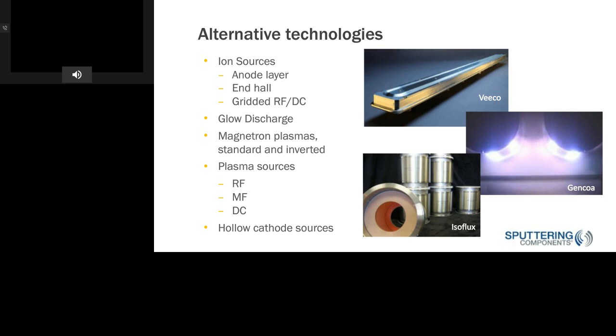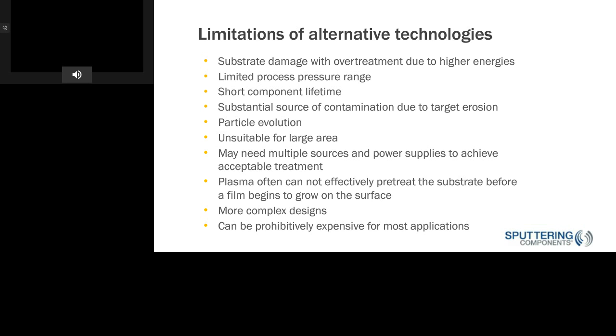slide. The main limitation really is substrate damage with overtreatment due to higher energies, and I'll show you a slide soon for the ion energies of this source versus competing technologies. The ion energies are typically much higher, and you can get substrate damage. There's also a limited process pressure range, especially with microwave plasmas. The pressure is usually too high for process stability. They have a short component lifetime. You have to change out the electrodes much more often, whereas we use a titanium electrode, and you'll see that in the design in the next slides too.